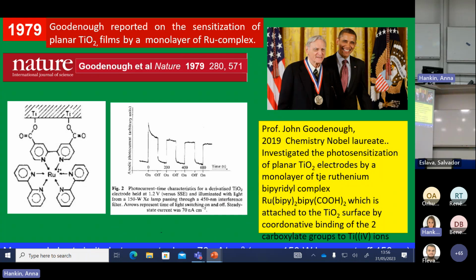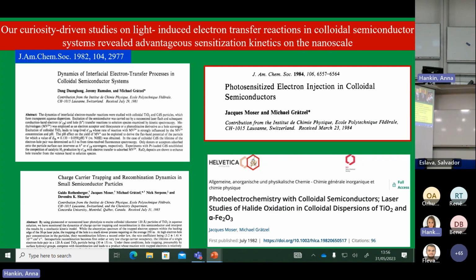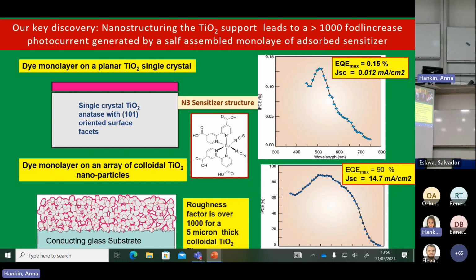However, I had invited John Goodenough to Lausanne, and at that time he was very interested in our studies on colloidal semiconductors. This, I have to tell you, was completely curiosity-driven. We were the first to make those colloidal solutions, and we realized we could excite the small particles with a laser. The solution looks transparent, and so you can do electrochemistry on the nanoscale using a laser to produce carriers. Years passed before we also sensitized these colloidal dispersions. I have to cut it short because otherwise 30 minutes would be on the history of that. Finally, what we ended up with, instead of using colloidal solution, was piling up the colloid on a conducting glass plate and sensitizing it with a carboxylated ruthenium complex. That was an idea that Goodenough had pioneered.